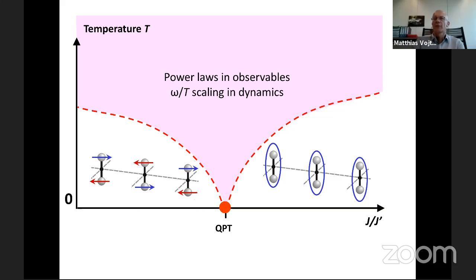What numerics can give you is, ideally, if you could do exact diagonalization, you can get the entire tower of states. And from this, you might be able to deduce the content of the elementary excitations. But I don't think there is any reasonable work in this direction. I think the work which has been done is DMRG, which essentially gives you ground state properties. And from this, you can't deduce the character of the excitations. So I think it's an open issue. There are some approximate solutions which indicate that there could be Majoranas, but this is not carved in stone.